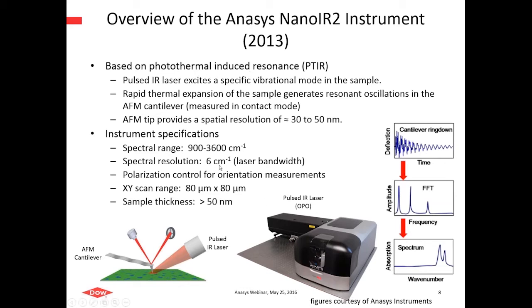Here are several of the key characteristics of the system, and then the picture in the middle showing the laser at the back, the steering optics here, and then the AFM is at the front of the system. And again, showing you the ring down due to absorption. It's with Fourier analysis converted to its amplitude and frequency components that can be tracked as a function of wave number, generating an infrared spectrum. Where there's no absorption, there's no kick to the lever, so no signal. Where there's strong absorption, there's a strong ring down and a larger signal to noise at that point.